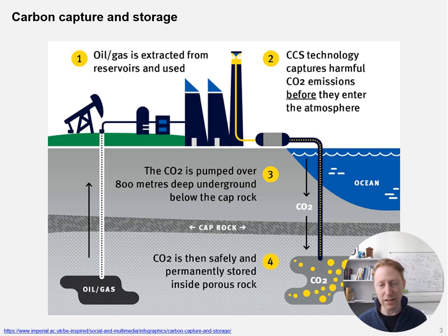A drawback is that carbon capture and storage does not produce a saleable product, so that means it relies on taxes or subsidies to be economically viable. Another consideration with carbon capture and storage is that it mainly is relevant to large point source emitters where there is a lot of CO₂ that can be captured. And from the last slide, you could see that CO₂ emissions from large point sources correspond to about half of all CO₂ emissions, meaning that there are a lot of CO₂ emissions which can be captured and stored in this way, but not all. And this means that carbon capture and storage has a large decarbonisation potential.